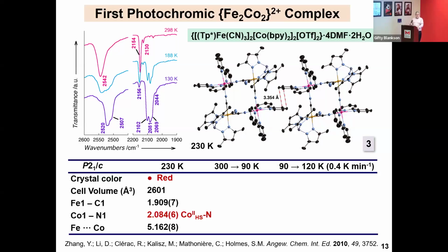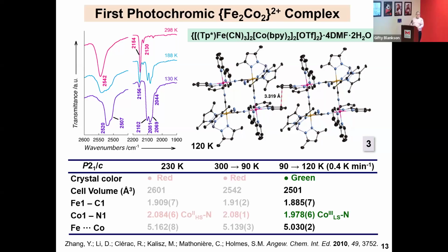Now, again, we looked at crystallography, and we were the first to show electron transfer from a molecular square. At high temperature, it's red, with relatively long cobalt-nitrogen distances. At lower temperature, quickly cooled, it stays red, because there's not enough time to relax. But if we slowly increase the temperature, it becomes green. What we did is we tricked the system.